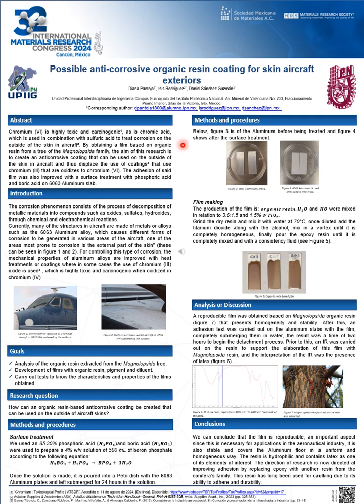By obtaining a film based on organic resin from a tree of the Magnoliopsida family, the aim is to create an anti-corrosive coating that can be used on the outside of the skin in aircraft and thus displace the use of coatings that use chromium-3 that oxidizes to chromium-6. The adhesion of said film was also improved with a surface treatment with phosphoric acid and boric acid on 6063 aluminum slab.